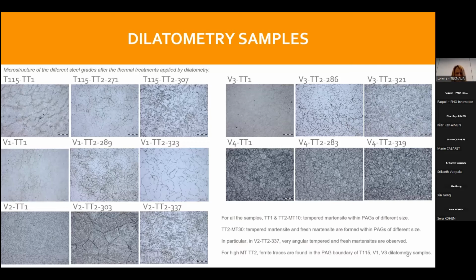In global terms, we can say that for all the samples, the standard thermal treatment and the TT2 with MT10 temperature give rise to tempered martensite with prior austenite grains of different size. In the thermal treatment 2 with MT30 temperature, tempered martensite and fresh martensite are formed with prior austenite grains of different size. In sample V2, for the highest MT temperature thermal treatment 2, very angular tempered and fresh martensites are observed.